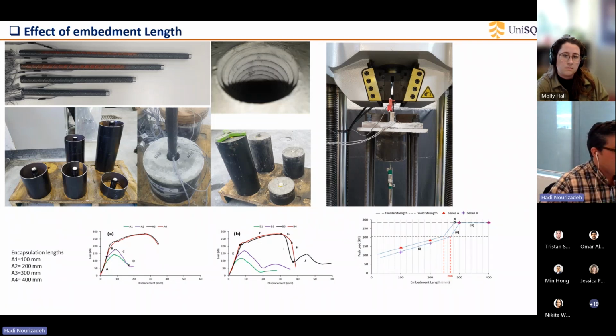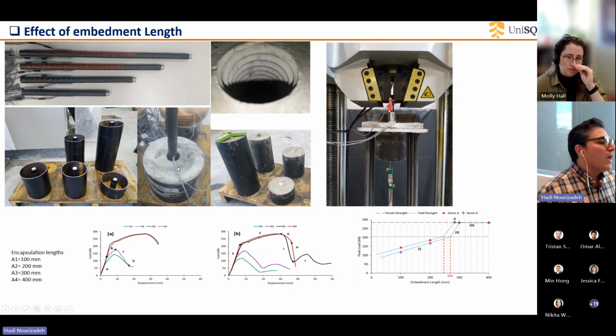One of the important aspects in the application of reinforcing elements in underground applications is the critical embedment length. What does it mean? It means that for this specific bolt, what would be the critical minimum encapsulation length? So we prepared some samples with different embedment lengths from 100 millimeters all the way to 400 millimeters with different bonding materials, including A and B. A is cementitious and B is a resin. We cast concrete with a UCS of 60 MPa and encapsulated our samples and carried out the pullout tests to see what the embedment length is and the effect of, for example, bonding materials on the critical embedment length.